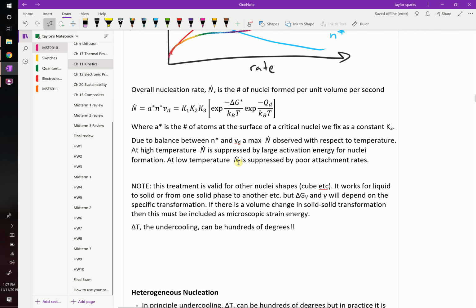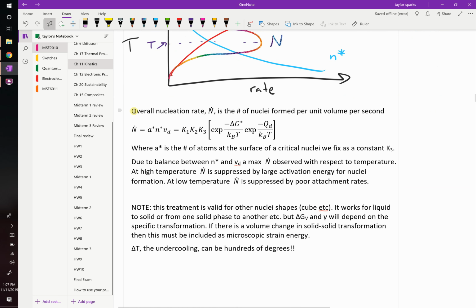Okay? So your overall nucleation rate, N dot, that's dN/dt, the change in your nucleation as a function of time, is going to be equal to A star times N star times V sub D. So A star is a constant. It represents the number of atoms that are near the surface. So remember, you've got your critical nuclei, and then your atoms out here that are going to attach to it, they have to diffuse over, but it's going to depend on how many of these atoms are surrounding it, how densely packed it is. That's what A star represents. And it's just another constant that we're going to use, okay? So your overall expression looks something like that, okay?